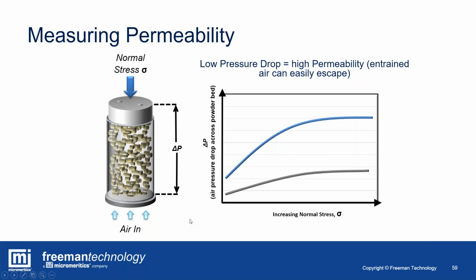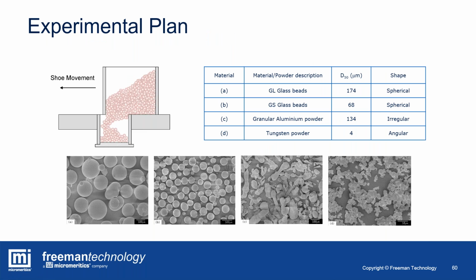So in this experiment, very simple, we wanted to design a simple experimental setup that we could build in our own lab. We had a shoe, which was a glass vessel. We could fill that to a specific volume, and we could prepare it by conditioning the sample first, so standardizing the density, and then it would move a single pass from right to left across the top of a die, which was a known volume, and we could do that at a specific controlled speed. And so we can establish how effective the material was flowing into the die based on the speed at which the shoe moved relative to the die, and also the material properties.